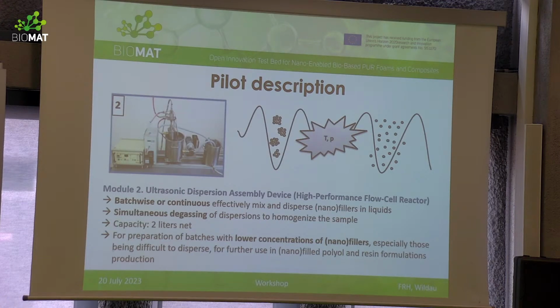The second module is supported with ultrasound, and in this case we can disperse different fillers at lower concentration in comparison with the 3-roll mill, but also we can disperse fillers that are especially difficult to disperse. Not only disperse, but simultaneously we can degas the dispersion. This is very important in the case of epoxy composite preparation. This module we can use batch-wise or continuously, and if we speak about batch, we are limited to 2 liters net.